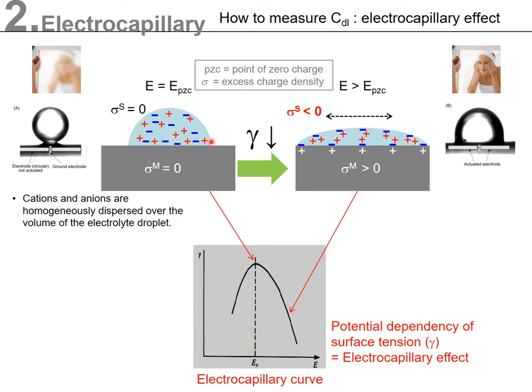Then I'd like to apply a potential to the metal plate. What happens? Let's go to the second situation. In this case, I have applied a positive potential, which is more positive than the point of zero charge. It means we have the excess charge, which is more positive than zero. So right now, we have 1, 2, 3, 4, 5 plus charges in the metal plate. This excess charge would affect the ions inside of the electrolyte. So, to compensate the 5 excess charges, the sign of which are positive, then 5 negative ions or 5 anions are accumulated on the surface of the metal plate. So 1, 2, 3, 4, 5.